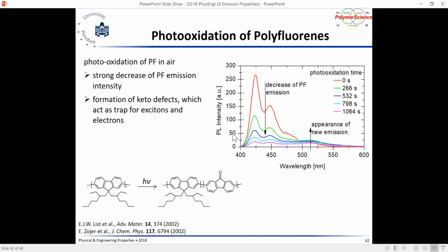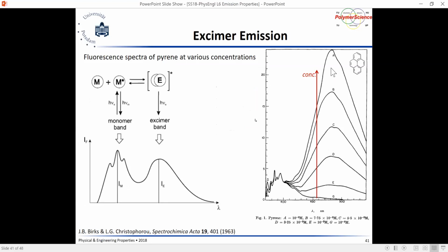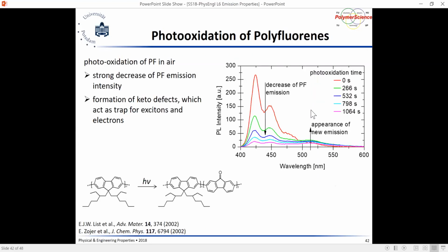There are many ways to change the intensity. Here the intensity of emission can change through concentration, and this is because when we have high concentrations, we can potentially have annihilation or even self-quenching. Another way of losing your PL intensity is photooxidation. A lot of our systems are actually sensitive to both oxygen and light, but in particular when both of them happen at the same time.